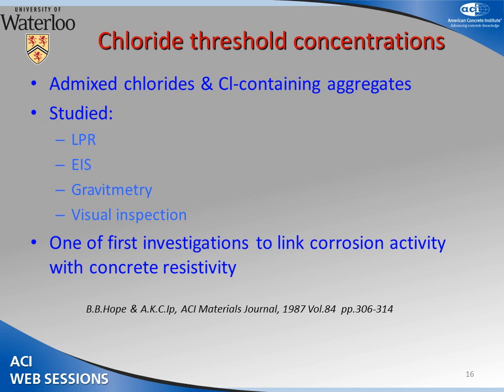Well, of course, if you're talking about chlorides, we also need to know what the chloride threshold value is. The chloride concentration necessary to cause corrosion. Well, today, of course, there are thousands and thousands of experiments that have been done trying to measure the chloride threshold. But this was one of the earlier ones. This is in 1987. And what he was looking at here was admixed chlorides and chloride-containing aggregates. And he studied this by looking at linear polarization resistance, electrochemical impedance spectroscopy, gravimetry, and visual inspection. And he was one of the first investigators to link corrosion activity with the resistivity of the concrete.